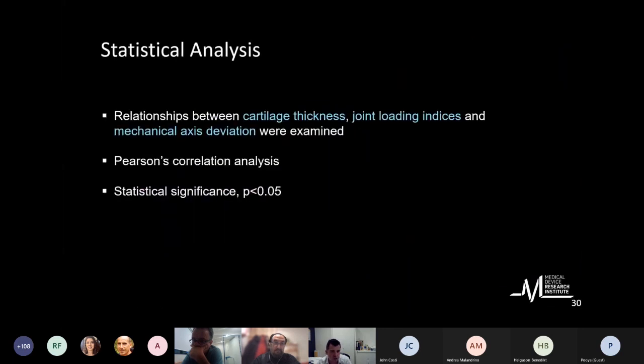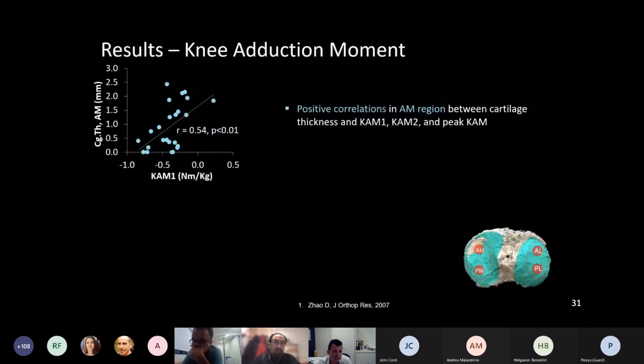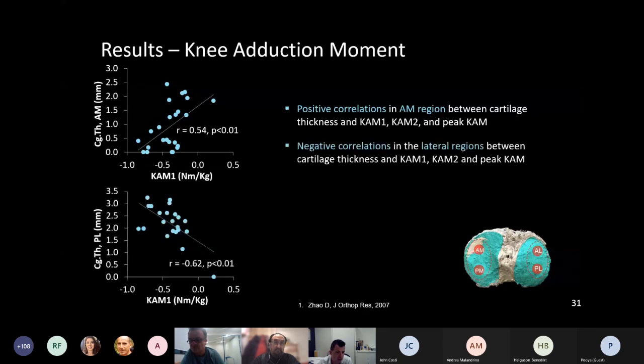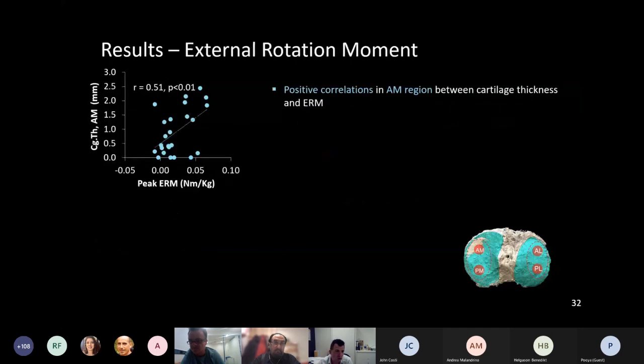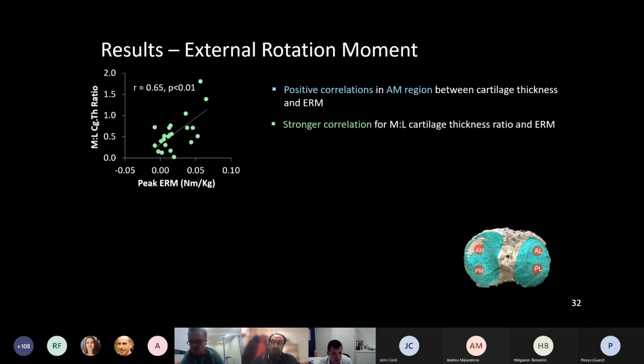And then we looked for relationships between the cartilage thickness, joint loading indices, and mechanical axis deviation. And what we see here is that there is a significant relationship, a positive correlation anteromedially with the knee adduction moment, and a negative one with the cartilage thickness posterolaterally, for example. Now, if we look at the external rotation moment, we find a significant positive correlation with the cartilage thickness anteromedially, and if we look at the medial to lateral ratio, this is an even stronger correlation.